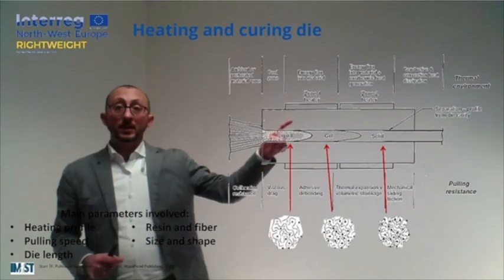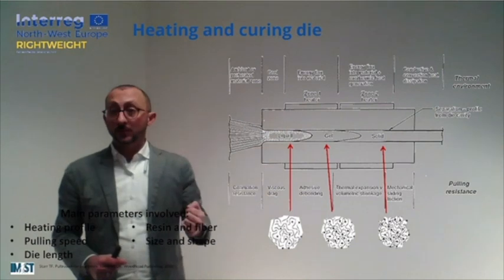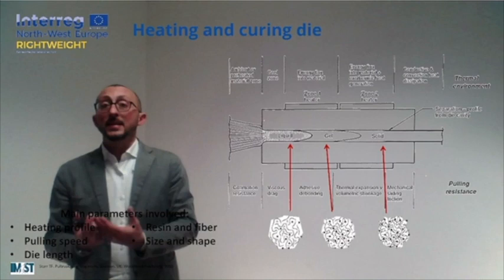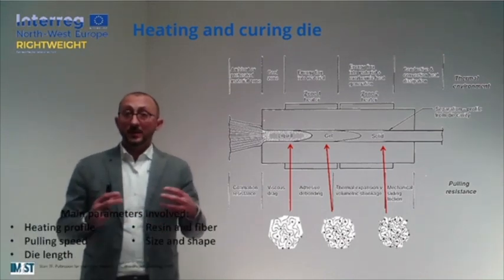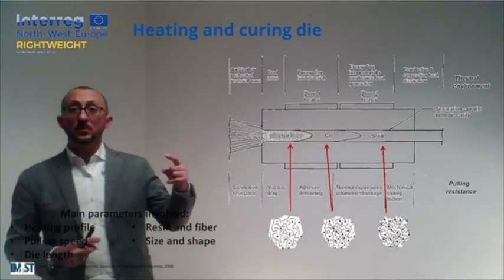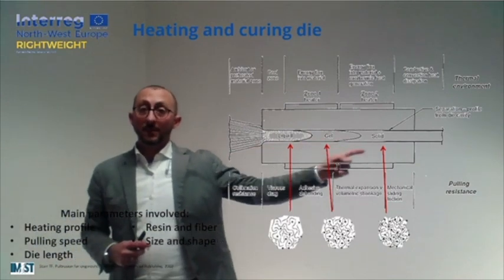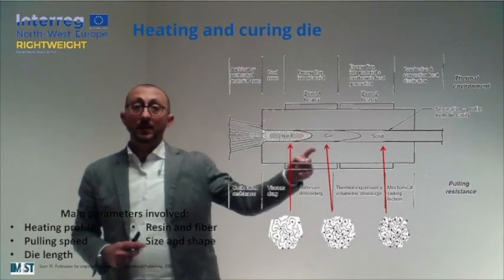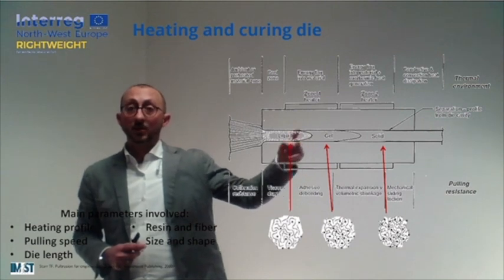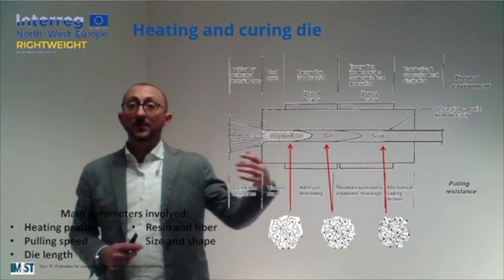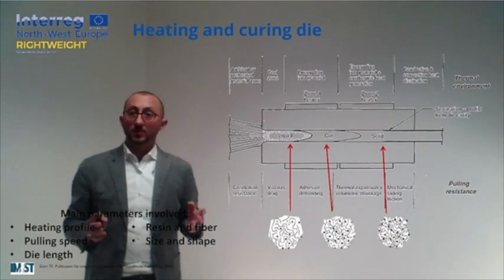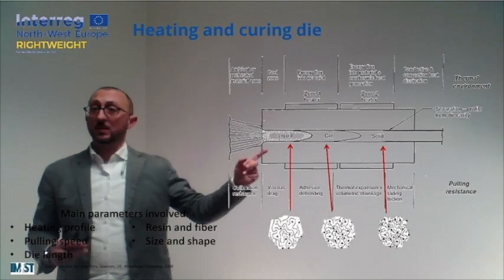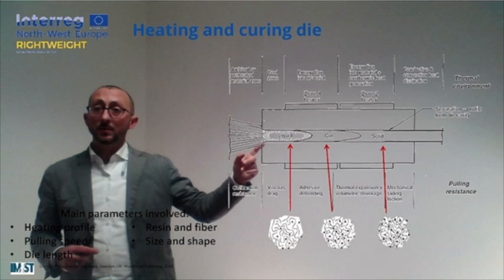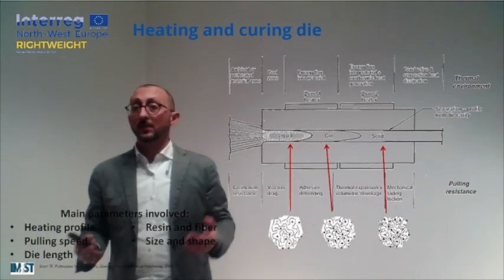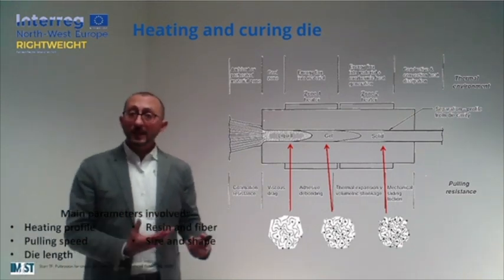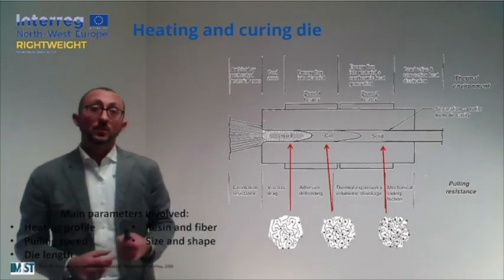After this point, thanks to the heat that is provided by our heating system, the temperature of our material will go up and the resin reaction will be activated. So the different monomers will start reacting, and we will reach, first of all, the transition from liquid state to the rubbery state. So after a while, it means that inside our die, we will see some kind of gelation, and crossing this surface, the interaction of the material with the die will completely change. Because of course, at the very beginning, we have some viscous forces, solid with liquid interaction, but after gelation, both of the materials are kind of solid, so we can think that some kind of friction is happening there, also with some variation in the friction coefficient.